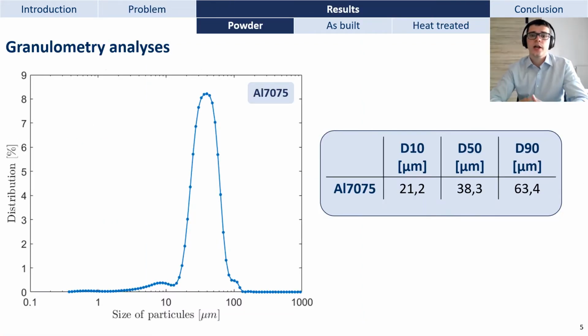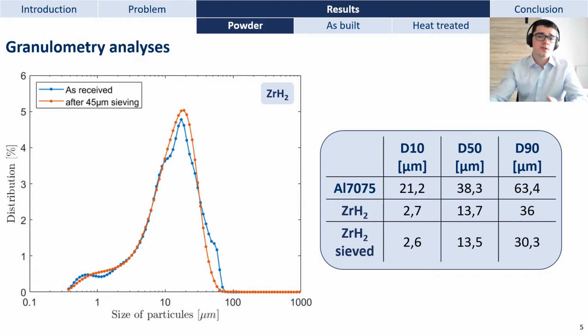So now let's get to the heart of the matter, beginning by analyzing the properties of the powder. First of all, here is the granulometry analysis of the aluminum 7075 base powder. You can see that it has a classical size distribution with a mean diameter of 38 microns. Now let us analyze the zirconium hydride powder. In blue, the ZrH₂ powder, and in orange, the powder after being sieved. It has a mean size around 13 microns for both conditions, but the D90 of the powder after sieving is 6 microns lower than before, and this effect can be seen on this graph.